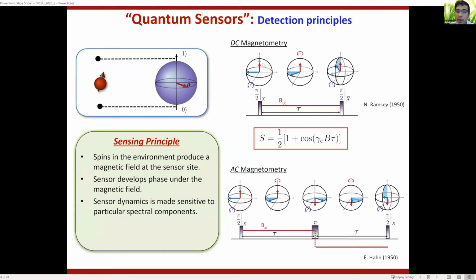You can also measure time-varying magnetic fields. And you can measure time-varying magnetic fields by doing the same trick here, but applying a pi pulse. So you only allow the spins to be subject to interactions that have a period that's given by this period tau here. And once again, the magnetic field information or the amplitude is imprinted in the phase of the spin, which then becomes a spin population, which you can read out.